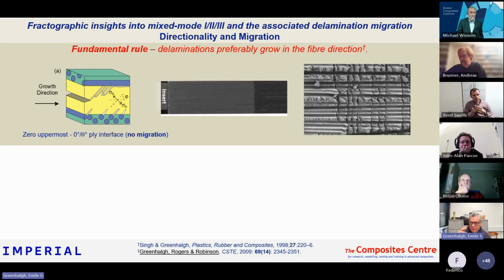But something you need to bear in mind is that if you have a 0-0 ply interface, the consolidation tends to promote nesting and you have a thinner interlaminar region. But in a 0-90, nesting isn't encouraged, so you end up with a thicker resin layer at that interface, and that in itself would tend to enhance the toughness. So you have to be quite careful in comparing a 0-0 to a 0-90, because it's not just the ply direction that changes, but the actual architecture of that interface.